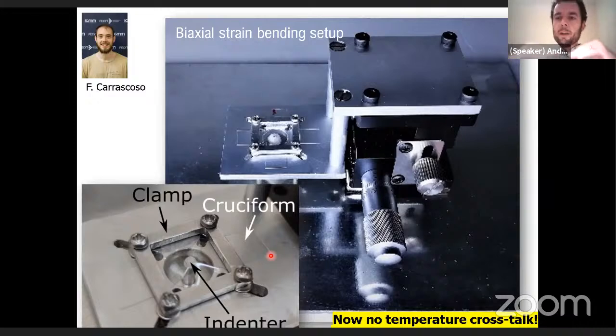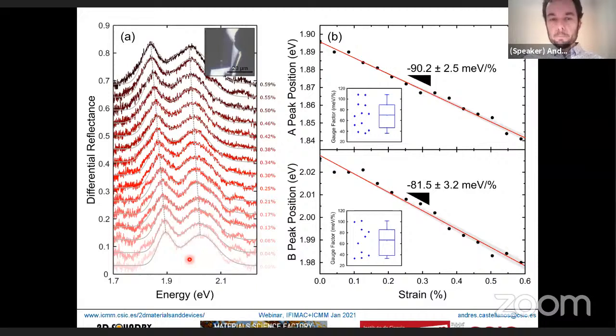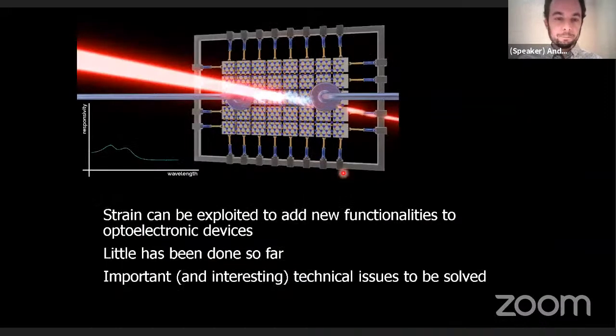Basically, the technique uses a bending scheme where we use a central indenter and a substrate that has a cruciform shape, so it has a cross shape, and we place our flakes right in the middle. Using this approach, you can indeed change the amount of strain you're applying to the material, and you can get nice strain tunable features. This is important because biaxial strain is a way more efficient way of tuning the band structure of two-dimensional materials than uniaxial strain, so having a method that allows you to apply biaxial strain in a controlled way is quite useful for straintronics and strain engineering applications.